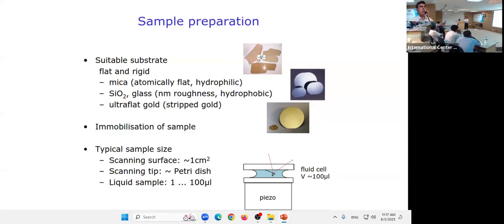But you know that mica contains many sheets. Once you load the sample and finish all your activity, you can reuse it by peeling off the upper layer with scotch tape. You just put the scotch tape on and then remove it, and then the fresh surface appears. So before loading your sample, you peel off the upper layer so that you do not encounter impurities. That is why in the literature you will always read the phrase freshly cleaved mica sheet. It means that you have removed the upper layer.